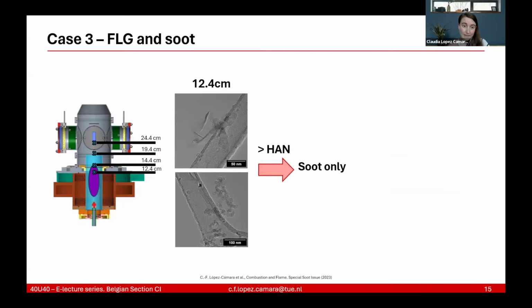For the third case, however, we saw that at 12.4 centimeters, which is the lowest sampling point, we got graphene and soot, as we saw. However, when we go to higher heights above the nozzle, so farther away from the nozzle, we could only see soot in the TEM, in the electron microscope. And that could have been happening for two reasons.